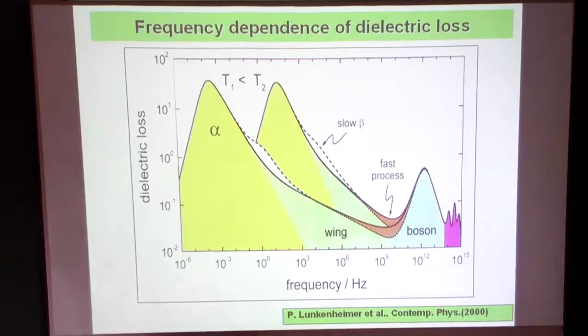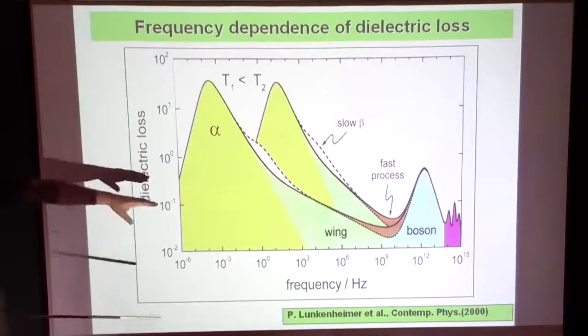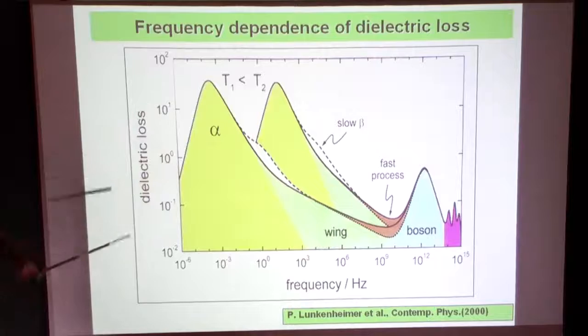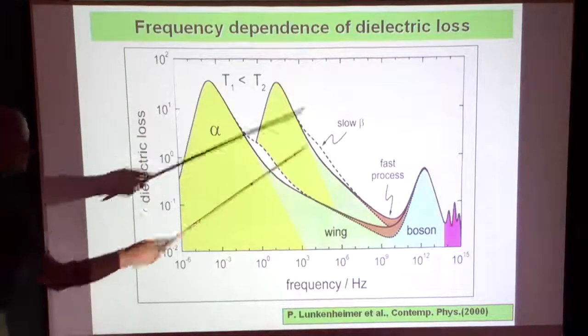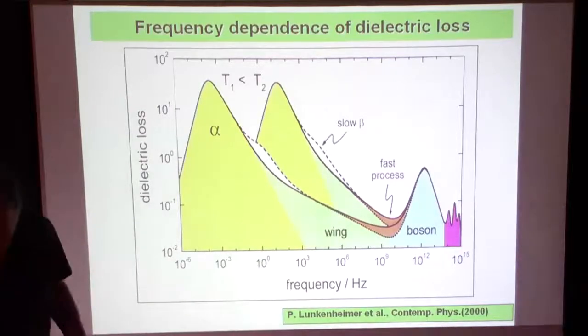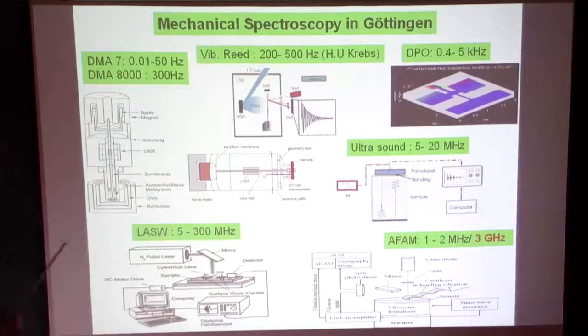So what are typical glass transition temperatures for these glasses? I come to that also, typically 300 Kelvin, but it depends on the composition very much. The interesting point of this diagram is that it is very universal. You find it in everything which is disordered. I don't know any example, at least in the liquids, in the disordered systems, biopolymers, polymers, metallic glasses, I'll show you in a minute, which doesn't have this kind of structure. We can't measure dielectrically because we have metals. So we built up in Goettingen quite a variety of systems to measure these objects mechanically.